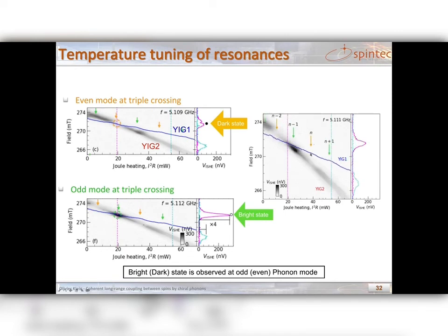These are measurements performed at different frequencies. And what you can see very clearly is that when you hit the triple crossing with an odd phonon line, green, it becomes a bright state. And when you hit the triple crossing with an even phonon line, which is orange, it becomes a dark state. You can clearly see this modulation through the magenta line, where you have a bright state here and a dark state here.